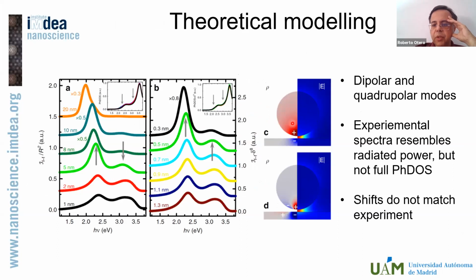The low energy peak corresponds to the dipolar mode. The high energy peak corresponds to the quadrupolar mode. And basically what we see is that our results compare well with the radiated power, but not with the full photonic density of states. For the full photonic density of states, the weight of the quadrupolar mode would be much larger, and that's not something that we observe in our experiment. Now, one might think that a spherical model for the tip is more or less like having a spherical model of a cow. We do have some ideas about that, and I would be happy to discuss at the end if that's of interest.